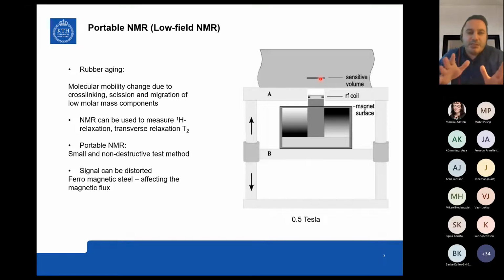And because of this limitation of the magnetic field strengths, it essentially limits us to work on the relaxations of protons which you have in your sample. The reason that we are interested in relaxation times, especially the transverse relaxation time, the T2, is essentially because T2 is very sensitive to molecular mobility. So when you have a polymer which is being aged and it's cross-linking and you're losing, let's say, even oil extenders from your materials, which is another form of degradation, you can actually detect that with the transverse relaxation, the T2 values.